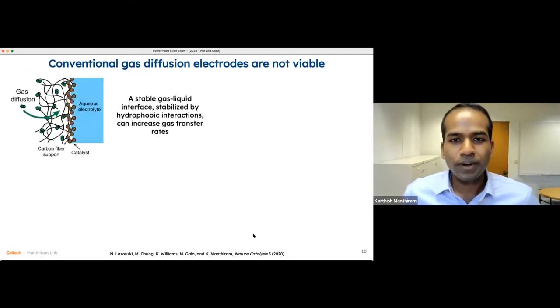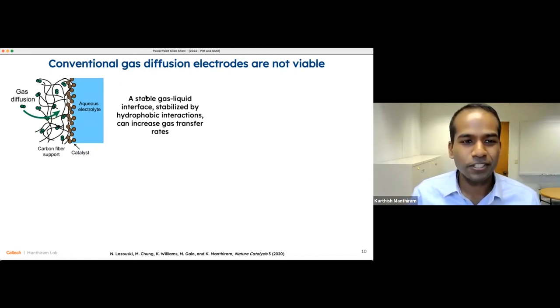So we can try to implement a conventional gas diffusion electrode. I show here one which is based on carbon fibers. This carbon fiber support has catalysts deposited on it. And with an aqueous electrolyte, this works rather well. A carbon fiber-based electrode does not wick up an aqueous electrolyte, and so it is not simply flooded.